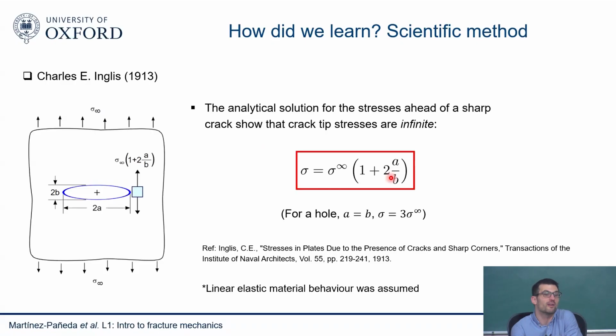One is that he assumed linear elasticity. Of course, if you assume plasticity, then your stresses will reach the yield stress, and then you get a distribution of stress, and you don't get these infinite stresses. But a lot of materials are linear elastic. Glass is linear elastic, so there will be some sort of non-linear stresses, but it's still reduced to quite a small area. So this result was quite puzzling to many people.